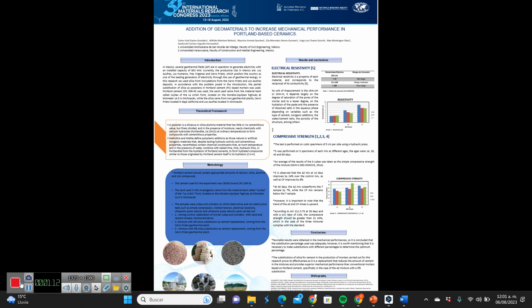located in Michoacán. For this research, it was decided to substitute silica obtained from the maintenance of the Los Azufres and Cerro Prieto geothermal fields because it has been shown to have cementitious properties. The percentage used as a cement substitution was 5%. The samples taken were cubes and cylinders, in which destructive and non-destructive tests, such as simple compression and electrical resistivity, were carried out.